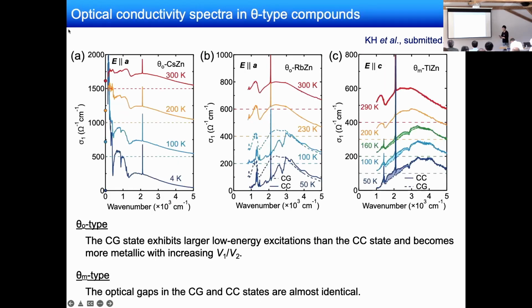Okay, and such a difference can be seen in the optical conductivity spectra of these materials. The optical conductivity spectra of theta-cesium zinc show very large low energy excitations, which is again consistent with the result that this material is located near the phase boundary. And so we measured the optical conductivity spectra in the charge crystal and the charge glass states. As you can see, there is a large difference in the optical gap between the charge glass and charge crystal states.